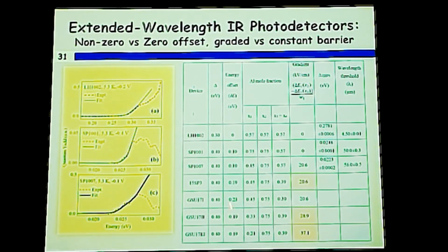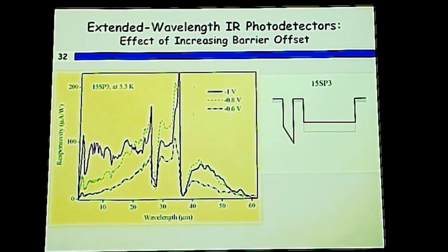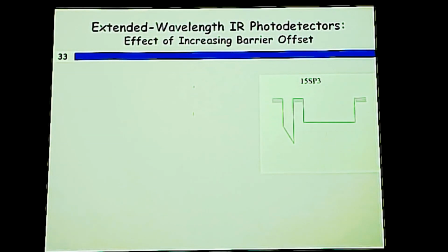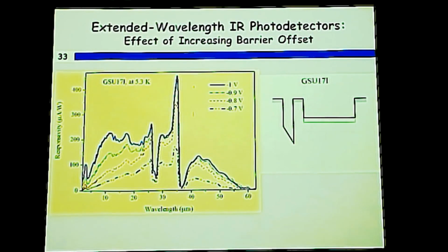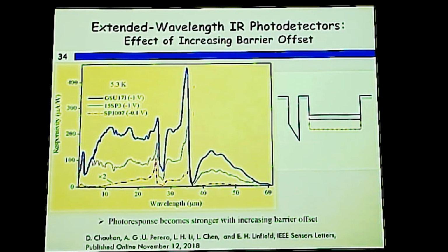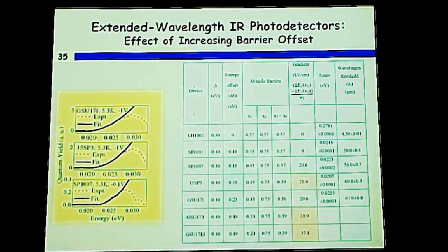So now from SP1007, we are going to these other 2 devices. 15SP3 first. These are the photoresponse results, and from this one to the next, GSU17I, these are the photoresponse for these devices. Now we have 3 devices and the photoresponse. By comparison of these 3 devices, we see that with increasing barrier offset, the strength of the photoresponse is also increasing. Looking at the wavelength threshold, there is a small variation, but overall the mechanism of the photoresponse appears to be similar.